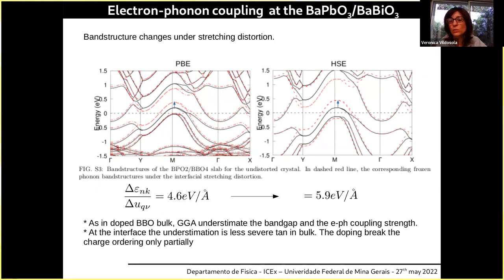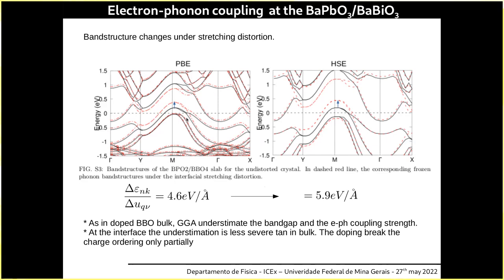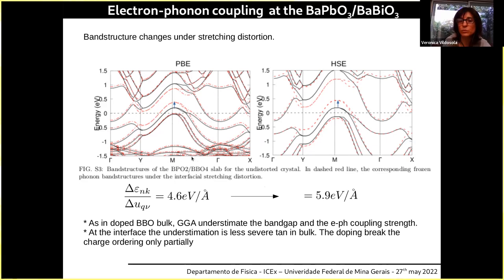But here, what I want to know is if the metallic states are artifacts of GGA or not, and that is what we have to convince ourselves of. But yes, these band structures are horrible to calculate. This is mainly a task done by Solange Di Napoli, I don't know if she's in the audience. What we do is test on only one segment, from M to half of the segment, and we try several things. When we are sure that we are at the right point, then for the paper we finish the full structure. To study, we only move around the main points, the M point and the gamma point.